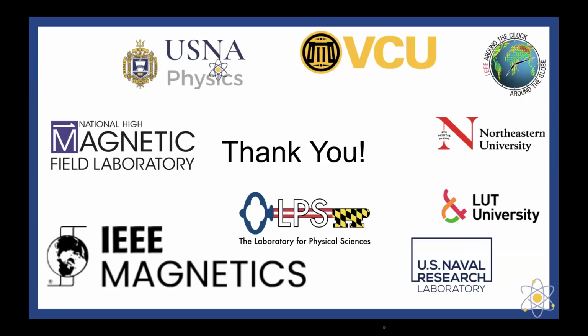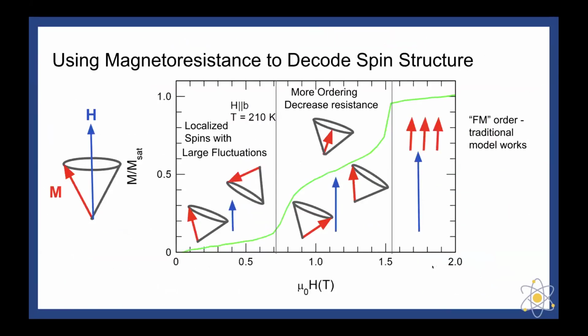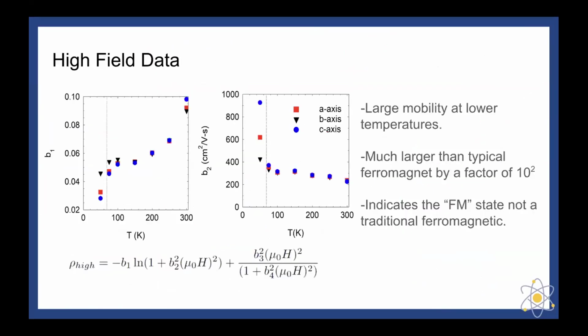Hi, Michelle. I have a question. So you mentioned that the mobility in this single crystal iron gallium is extremely high. But I want to know the reason why it's so high, because although you said that it's not actually a ferromagnet, in one figure you show that it's saturated at around 2 Tesla. Actually, it has some, I believe, ferromagnetic behavior. So I want to know how the mobility, because in generally ferromagnetic material, the magnon-electron scattering causes the mobility to decrease. What's your thought there?